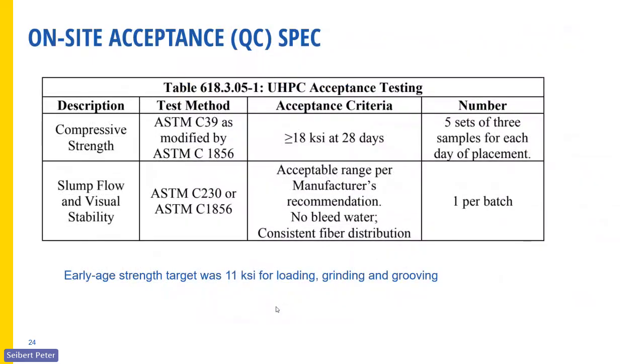But on the job itself, the only QC that was done was compressive strength testing for every day we were producing or placing UHPC, and flow tests were done. The flow tests were done just to make sure that there's a consistency of the material, that it's always the same visually, and that it's the same from batch to batch, which is very important for UHPC, because you want to have the consistent material in front of the paver. You don't want to have the paver to stop and go. It all has to work together like a symphony.